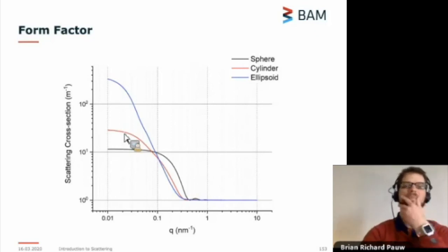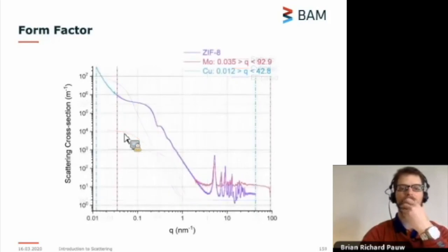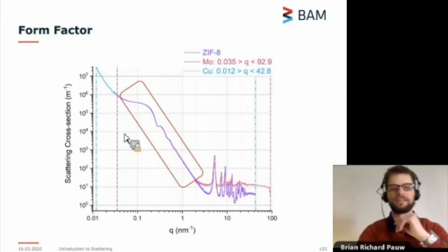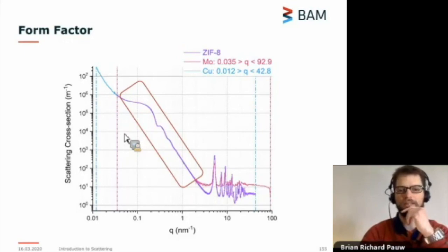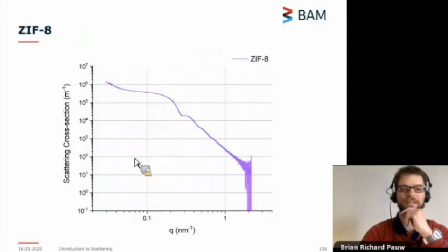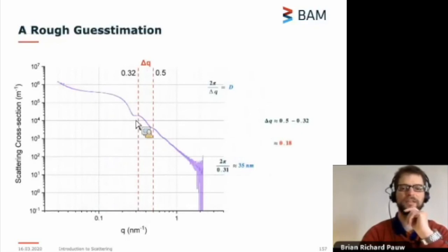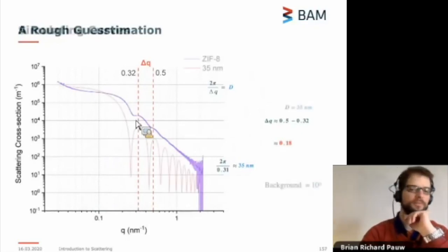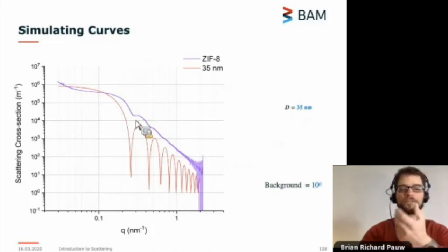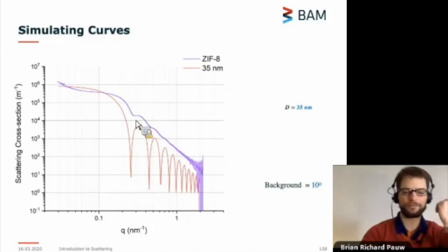All right, so this section, how do we start analyzing this? I won't go through the complete analysis here. I don't have time for that really. But normally what we do if we see these oscillations is that we estimate the approximate size of the object, which in this case is 35 nanometers. And then we can start describing this, for example, with a sphere. If we describe this with a sphere, it looks similar. Well, the bumps are in approximately the right place, but these dips are not there.